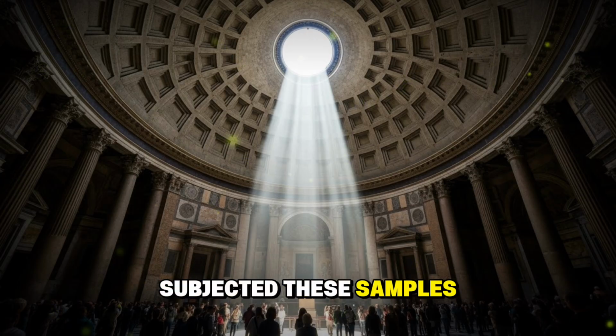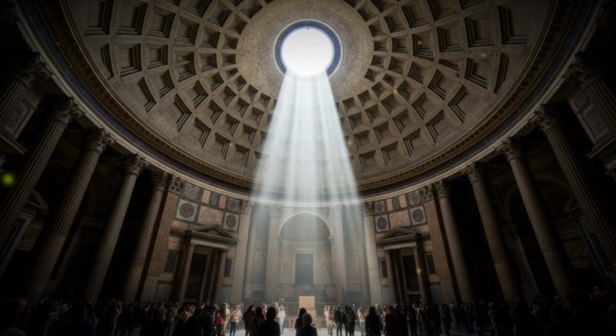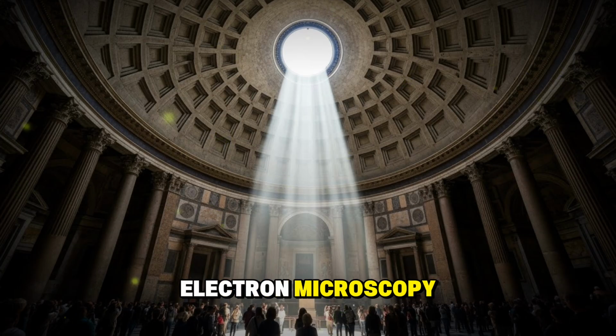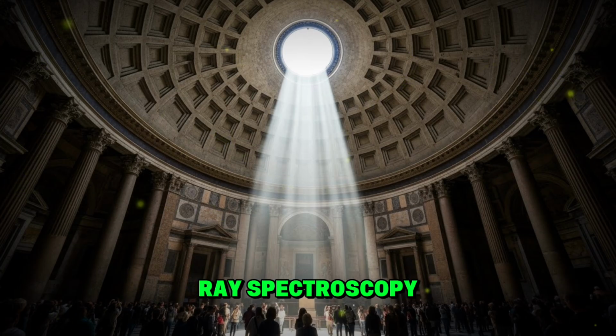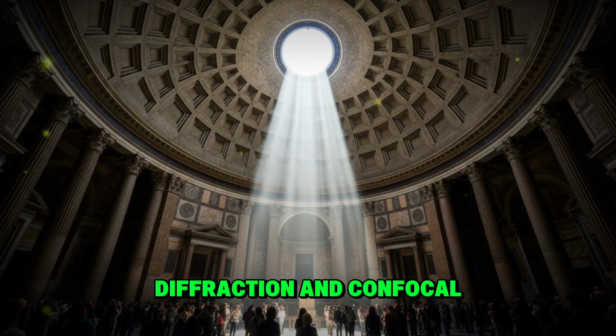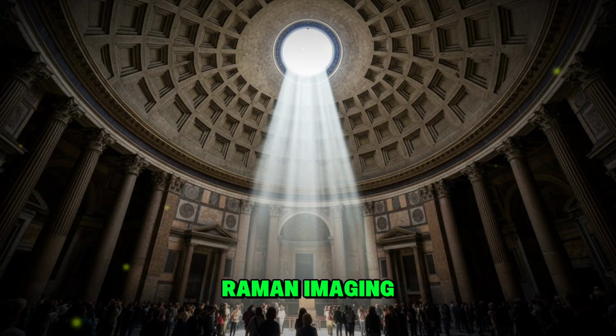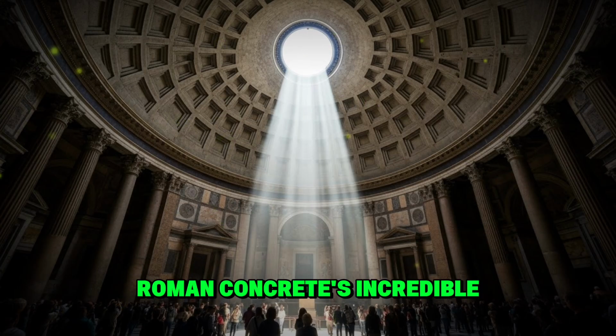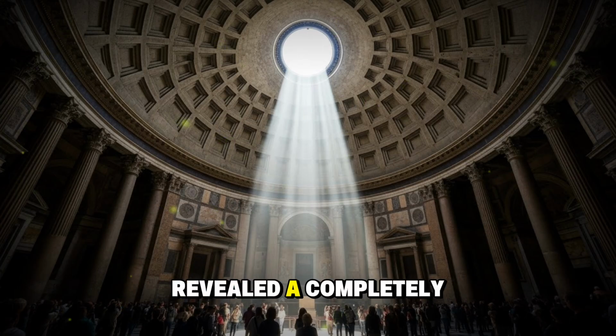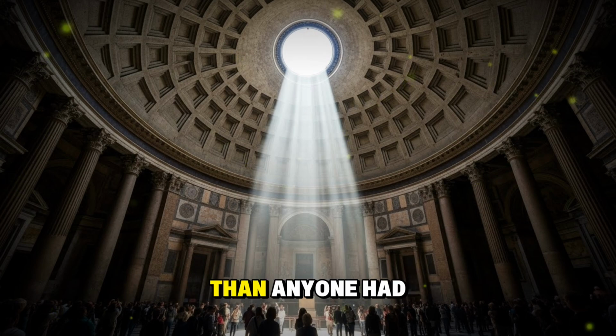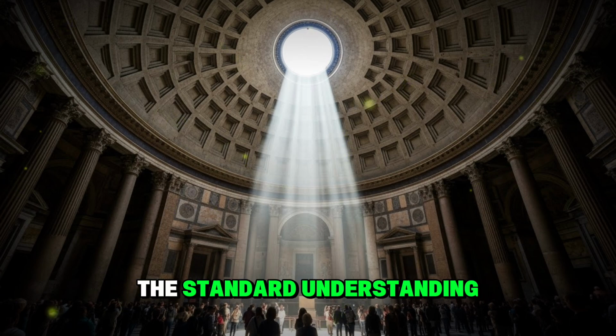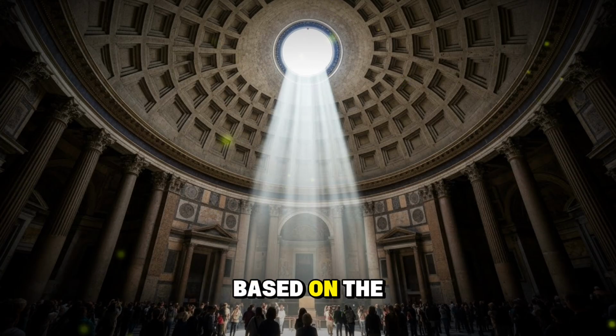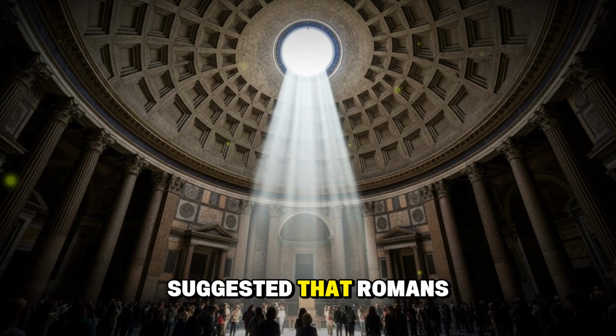They subjected these samples to advanced imaging techniques: large area scanning electron microscopy, energy dispersive X-ray spectroscopy, powder X-ray diffraction, and confocal Raman imaging. What they discovered was that these lime clasts were not evidence of poor quality. They were, in fact, the secret to Roman concrete's incredible durability, and their presence revealed a completely different production method than anyone had suspected.